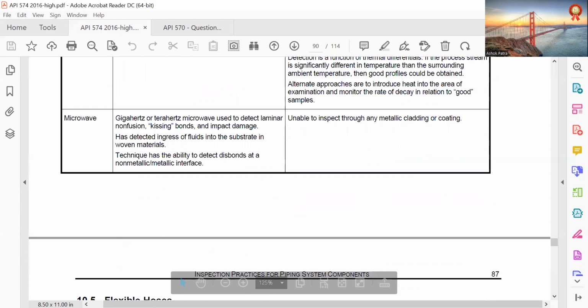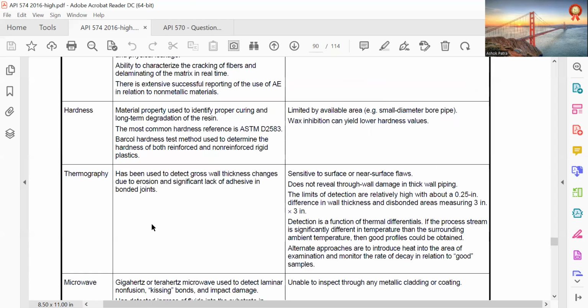Microwave, gigahertz to terahertz, is used to determine laminar non-fusion, kissing bonds, and impact damage. It has detected ingress of fluids into the substrate in woven material. The technique has the ability to detect disbonds at a nonmetallic/metallic interface, but is unable to inspect through any metallic cladding or coating. It has been used to detect gross wall thickness changes due to erosion and significant lack of adhesive in bonded joints. It is sensitive to surface and near-surface flaws, and doesn't reveal through-wall damage in thick wall piping. The limit of detection is relatively high, with a 0.25-inch difference between wall thickness and disbonded areas measuring 3 inch.